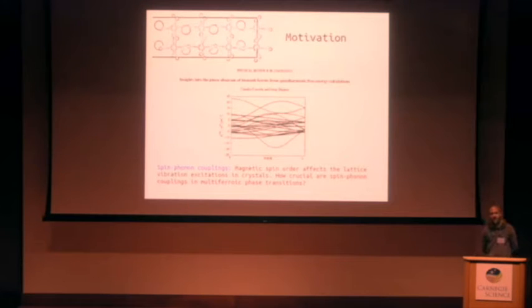Because of that, a few years ago with Jorge Iñiguez, we started wondering how important spin-phonon coupling effects could be in multiferroic compounds, in particular in multiferroic phase transitions. So what does this spin-phonon coupling mean? As a matter of fact, when you consider different magnetic orders in bismuth ferrite, your phonon vibrations change, right? This is a calculation based on DFT in which we calculated the phonon frequencies by constraining the magnetic moments to the ground state, which is antiferromagnetic order G, or adopting the ferromagnetic state in which all the magnetic moments are parallel, right? By doing that, you can then identify one by one the eigenvectors in the two states, and then calculate this omega shift, right?